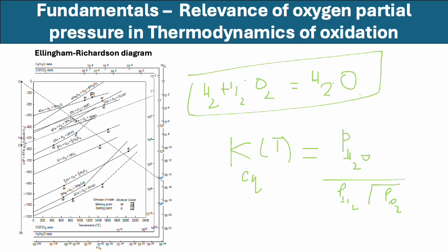So indirectly, this is also representing this. I am taking H2 by H2O ratio by convention, but if I want to equivalently represent a partial pressure, then I can convert that. This is equal to PH2O by PH2. So we need to consider PH2O by PH2, and then in the denominator we have the equilibrium constant K. So this is the inverse of this number that can represent equivalent oxygen activity in the environment where this reaction is taking place.